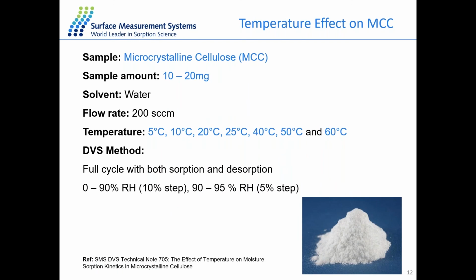And the case study here for the DVS data, we would like to investigate the temperature effect on the moisture kinetics of this microcrystalline cellulose sample. So we performed the same experiment as previously introduced, from 0 to 95% RH with 10% intervals. And this time we performed experiments at a series of different temperatures, from 5 to 60 degrees. The amount of sample for all the experiments is just around 10 to 20 milligrams, because the microcrystalline cellulose sample has quite a significant uptake for water.